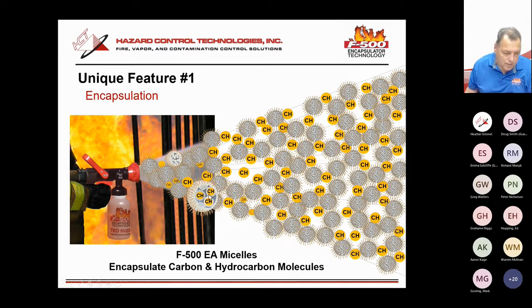So basically what we're doing is we're encapsulating the fuel molecule inside the spherical micelle. Now, the reason we have 15 fixed system projects at the Tesla Gigafactory is because we went to Tesla, met with Tesla and Panasonic, and they said, look, this electrolyte is flammable. Show us what this micelle can do. So they gave us the electrolyte. We put that in a pan. We put our agent in the pan. We mixed in water, and we encapsulated Panasonic's electrolyte.